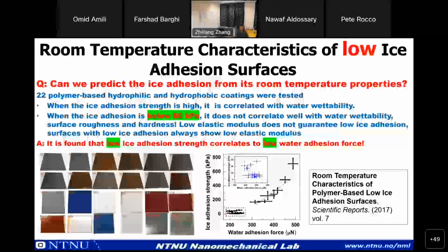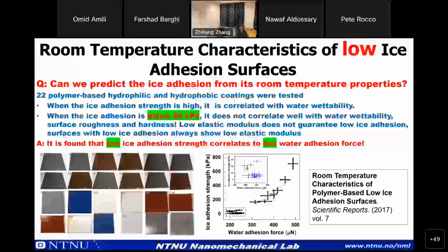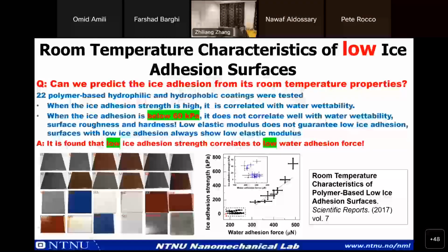We found that when the ice adhesion strength is high, for example higher than 200 kilopascal, there is a correlation between the low temperature ice adhesion strength and the room temperature wettability. This is the same as what we have seen from the literature. However, when the ice adhesion is below 60 kilopascal, it does not correlate with the room temperature wettability anymore. It does not correlate with the surface roughness as well, and does not correlate with the hardness.